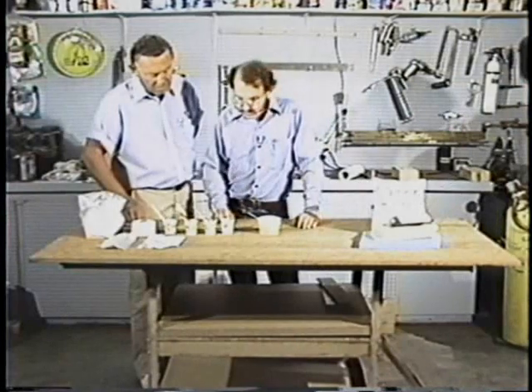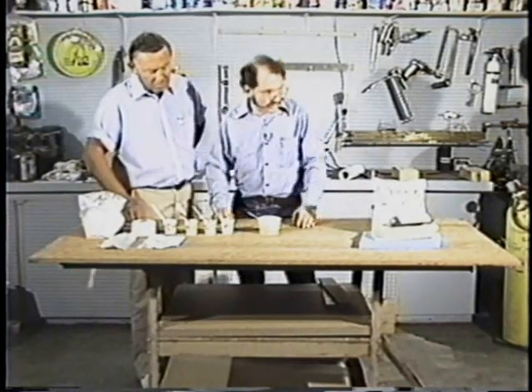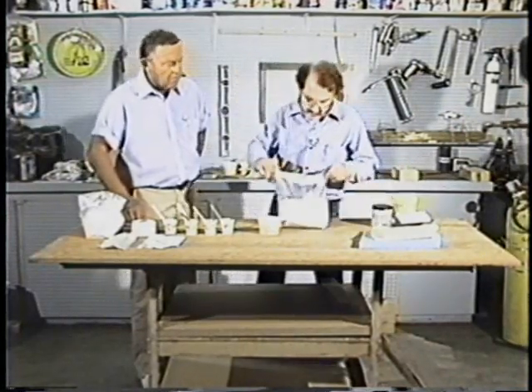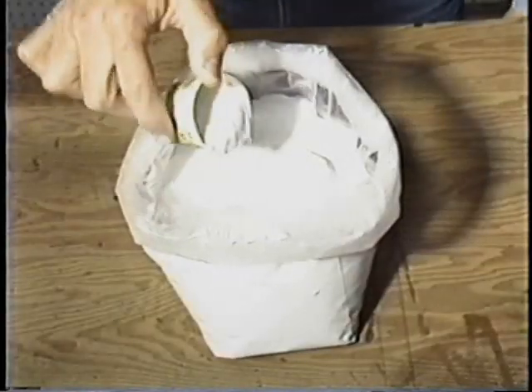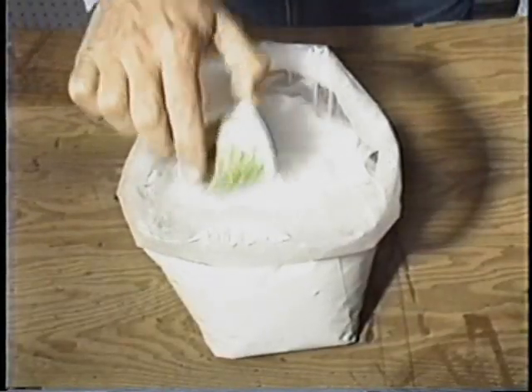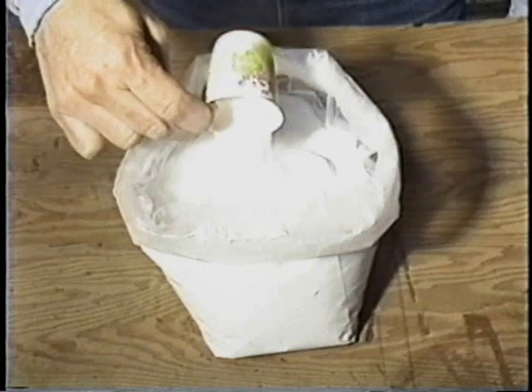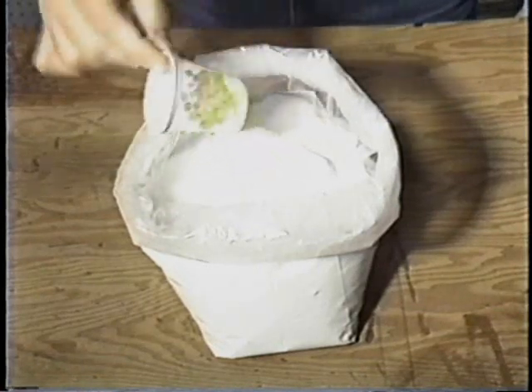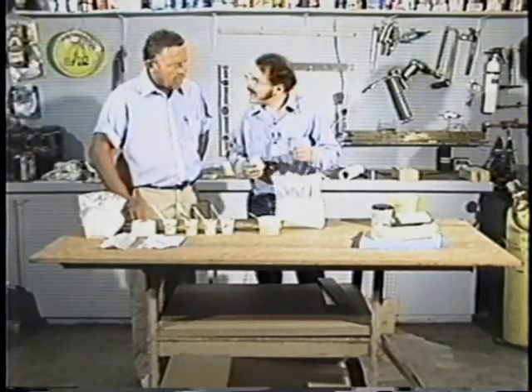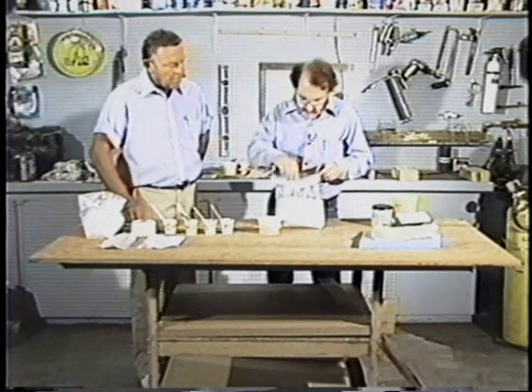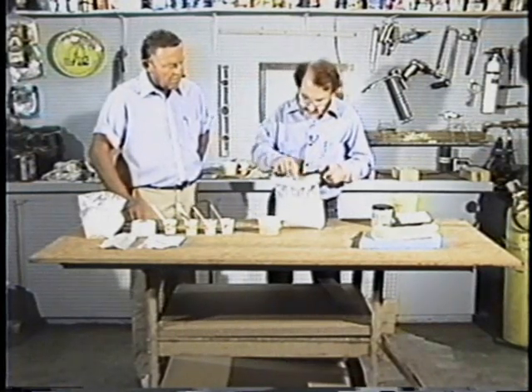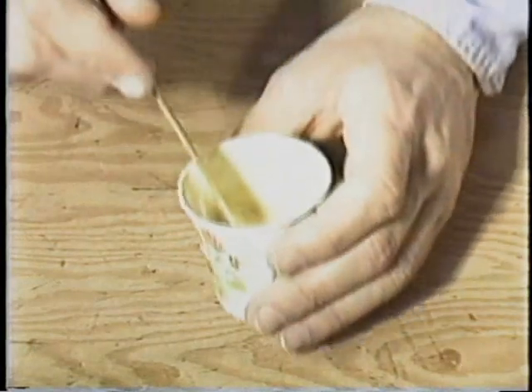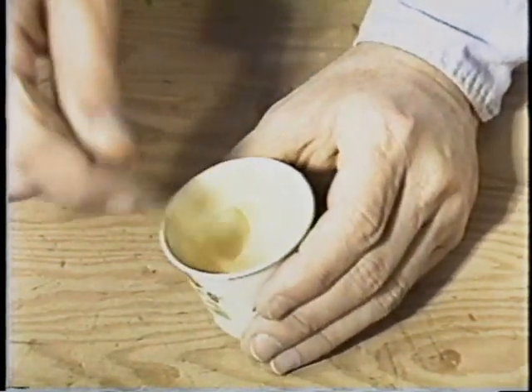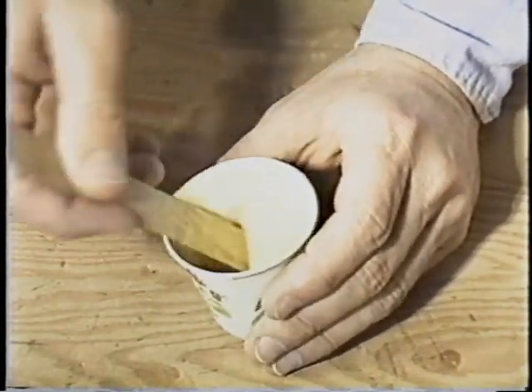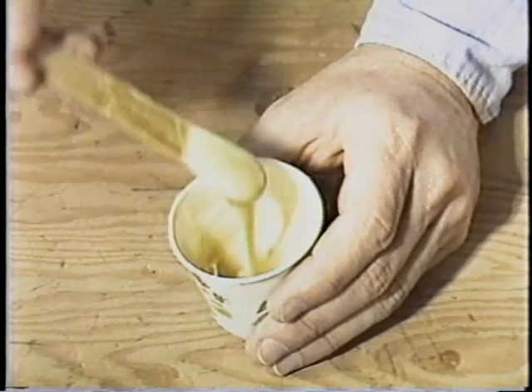The filler for the first 3 of these is micro balloons. These are micro balloons. This looks about the consistency of flour. Very, very fine, very, very light material, and each grain is actually a glass bubble. Micro balloons are simply a means of reducing the weight of an epoxy resin. A 50% mixture of micro balloons to epoxy gives you micro slurry, a liquid which is nearly as runny as epoxy, but only about half the weight.